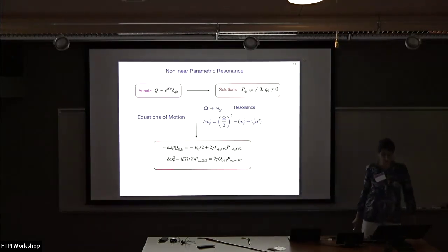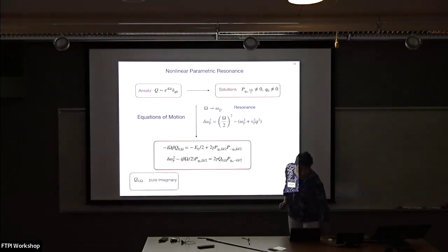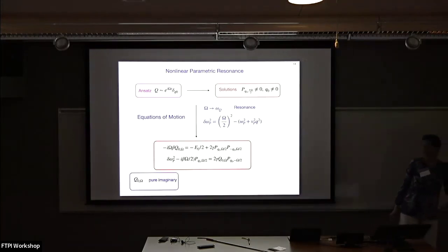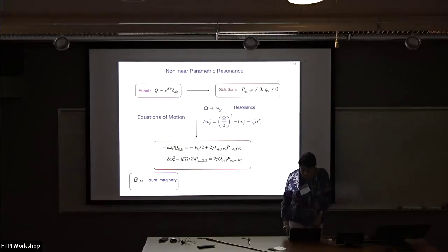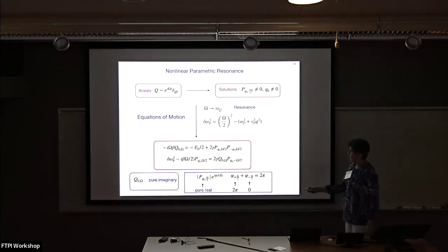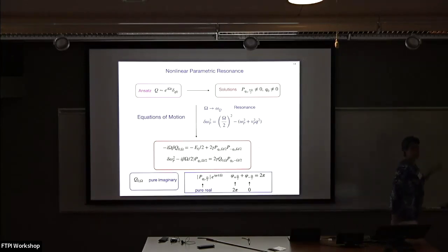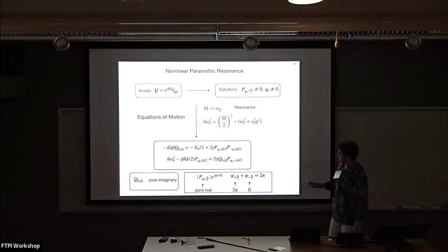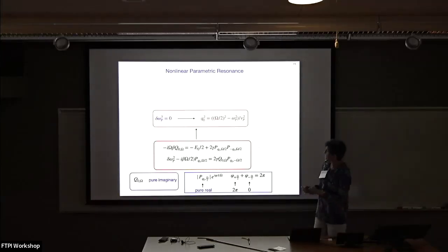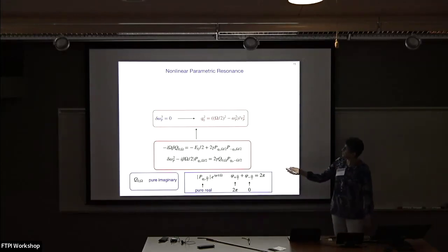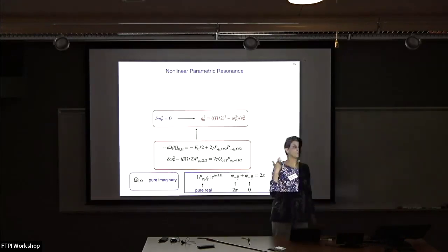Well, we plug them into our equations of motion, and we get this. And now, because we're at resonance, Q is imaginary. And it turns out that the structure of the equations gives us a form like this for P. And at t equals 0, the initial phases are set by the initial conditions. So we can decide to set the phases at 0 and 2 pi, which means that this has to be pure real. Well, if this is pure real, this is imaginary, this guy better be 0. So as a result, if this is 0, that gives us a condition for Q0, which, as you see, is going to be a function of our drive frequency, omega p, and the dispersion.